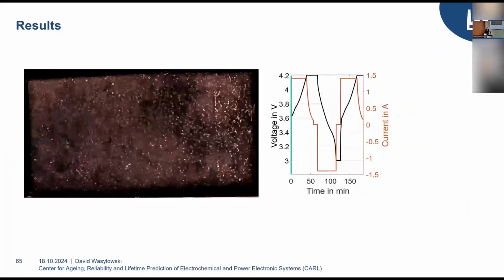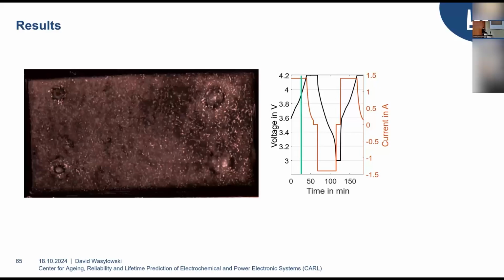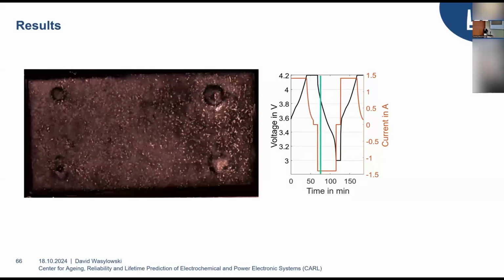So if we want to visualize lithium plating to assist during fast charging processes, we need to charge the cell and make these ultrasound images in real time. And on the left side, you can see the ultrasound images, and on the right side, you can see the associated electrochemical procedure, so the fast charging protocol here. And when we now start to charge the cell, we can see those indications arising exactly where they were in the first image, so around these adhesive dots, and they actually grow during charging. So this is giving us a good hint that this is actually lithium plating, because this is very typical behavior for lithium plating. And if we now discharge the cell, we can see those indications shrinking.